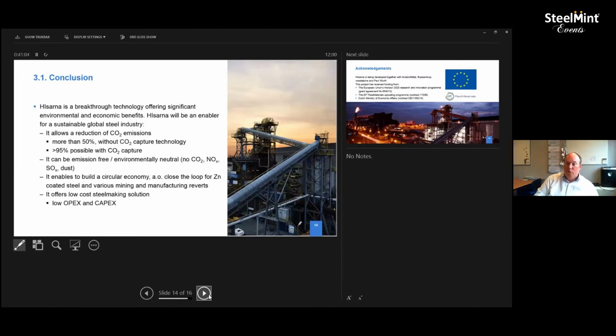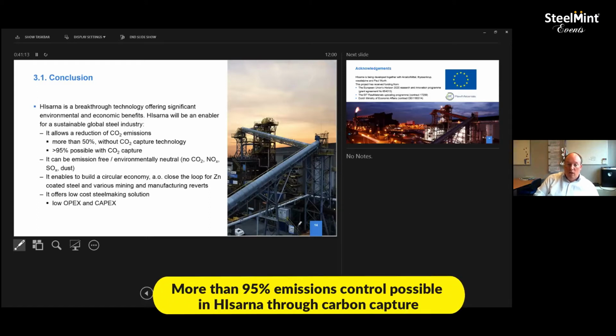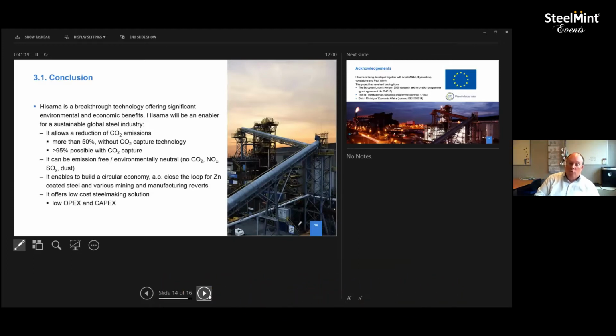We've proven 50% without carbon capture. We think more than 95% is possible with CO2 capture if we get it right. It can be emission-free, environmentally neutral, and that means that not just the CO2, but also nitrous oxide, sulfur oxide, and dust emissions are much reduced. And it can contribute to a large extent to a circular economy. We're focusing on zinc, but we also see opportunity for recovering other materials from either dust or slag streams from the process. And on top of that, it offers a low-cost steelmaking solution.